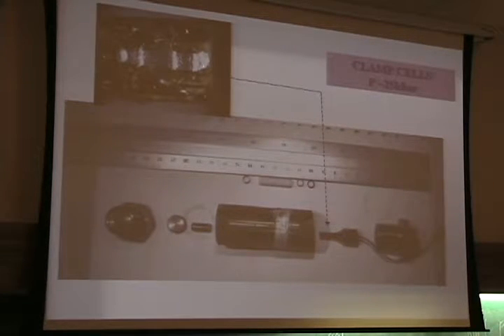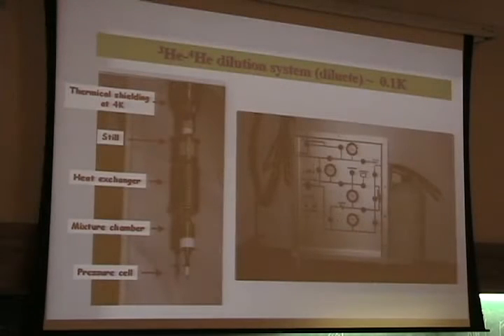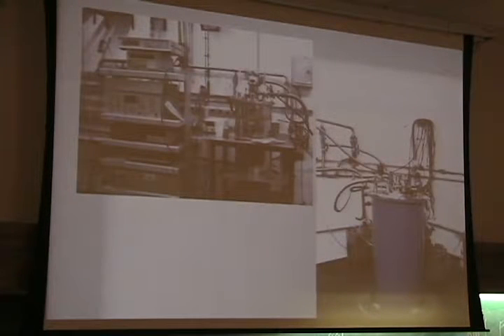And this is a typical installation for a sample that is maybe 1 millimeter by 3 millimeters long, with normal, let's say, silver paint. We have a dilution system that can go down to 40 milli-kelvin, but when you put the pressure cell, in general you can only start from 100 milli-kelvin, because the cooling power is not so big for these pressure cells. You generally make AC resistivity measurements.